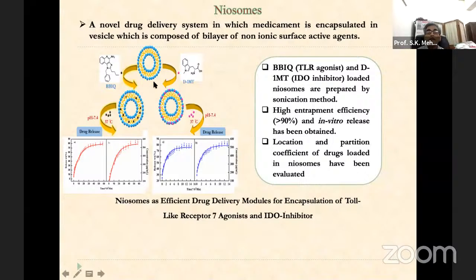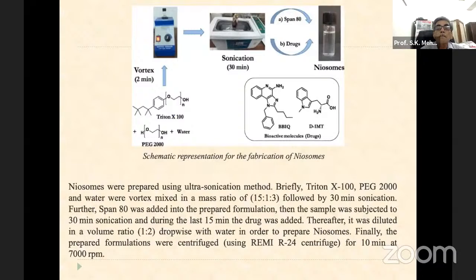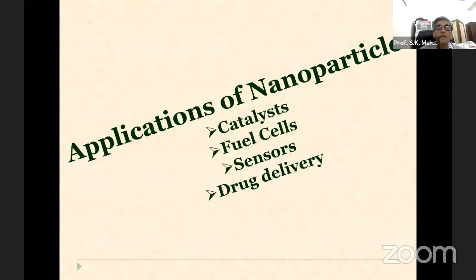So we found that we could achieve high entrapment efficiency, and in vitro release also was very good. And the location and partition coefficient of the drug loaded in niosomes, we could evaluate. So these are release studies. One can see how slowly the drug is released, because the ultimate purpose is to send the drug in the form of this formulation into the body, so that there is a slow and effective release, and the drug can be used effectively and for longer. So these are the methods we have used, with Triton X100, PEG 2000, and so on.